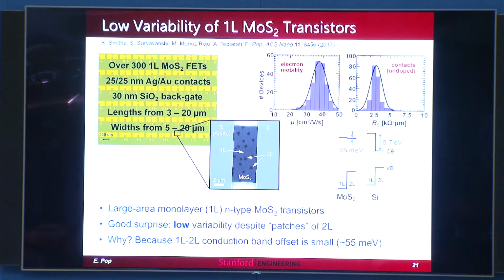To make a long story short, it turns out that I was almost needlessly worried in 2016. Maybe I worried too much. It turns out that the variability that we see in these samples is actually significantly lower than you would expect for something like silicon that would, if you were assuming silicon to vary by 100% in thickness. And so we catch a break. The break has to do with the physics, or the chemistry rather, of the material.